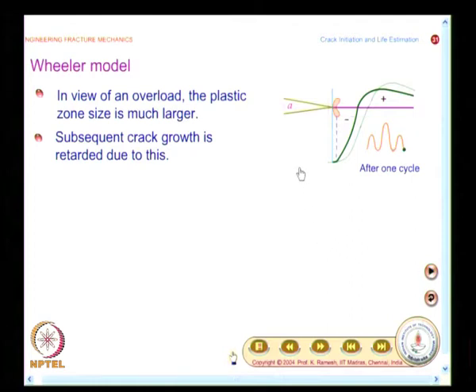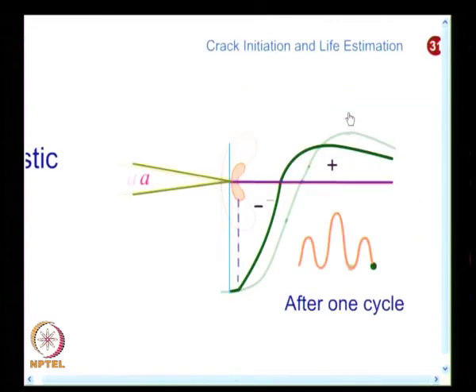So, this is the other picture you have. The subsequent crack growth is retarded due to the overload plastic zone, and you have a picture for that. I will also zoom it for you. So, what are we looking at? We are looking at after the smaller load. I have this crack as advanced, you have the smaller plastic zone, but this plastic zone remains in the overload plastic zone. So, the rate of crack growth will not be as high as it was before, it is now retarded.